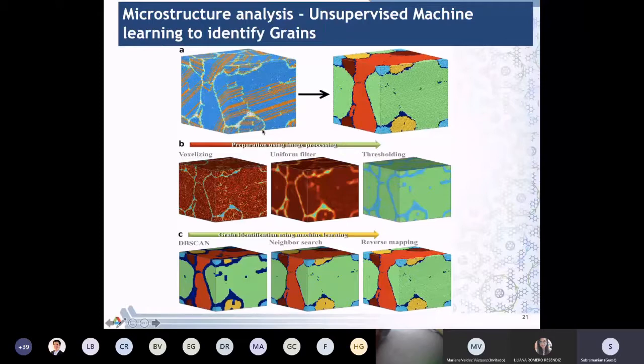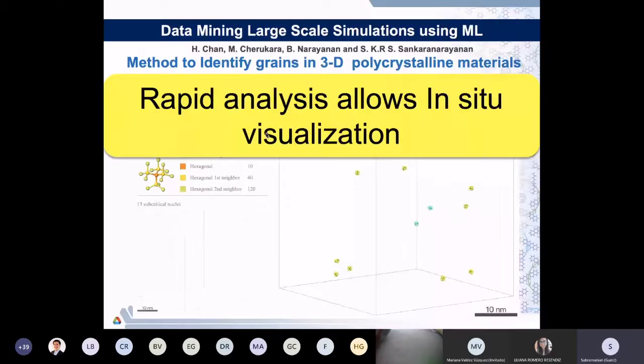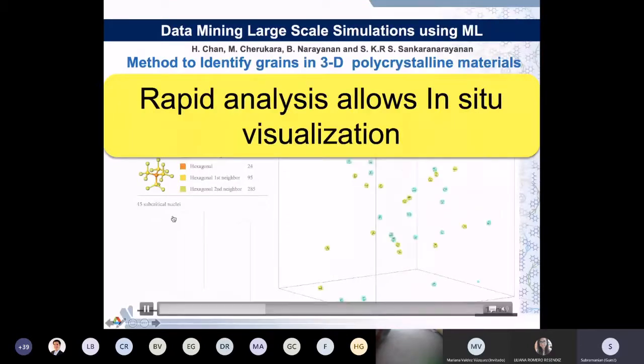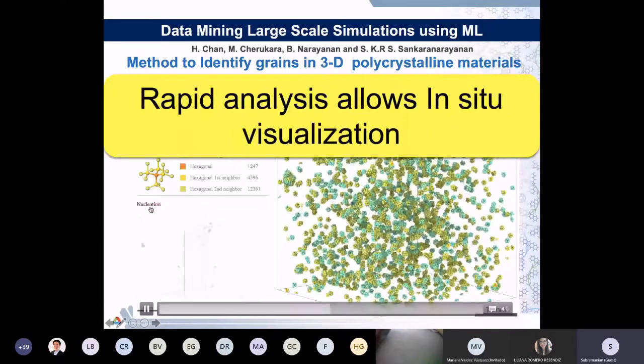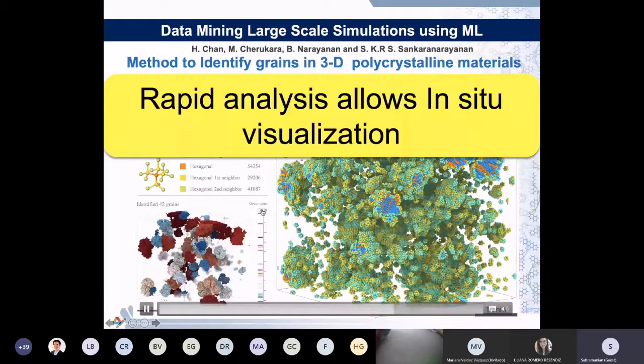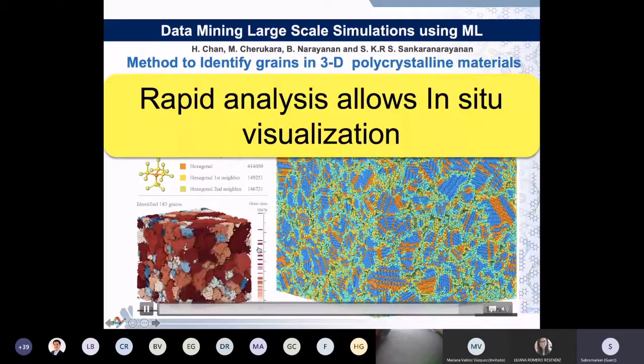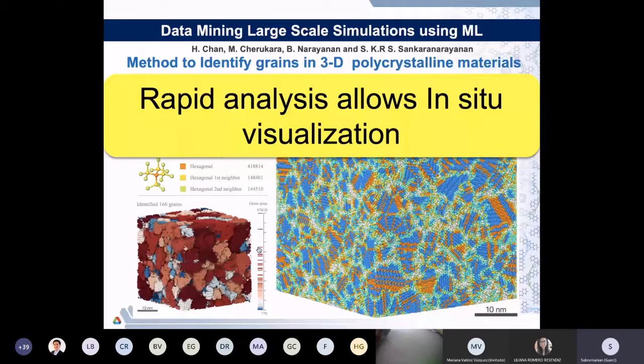The advantage of that is that as you are performing the simulation, you can actually do the analysis of how many grains are actually forming, whether they are subcritical, whether they are critical. And so you can actually map the grain size distribution in real time. So this is actually real-time in situ visualization as you are carrying out these large-scale multi-million molecule or billion molecule simulations. This actually takes only a fraction of a second to do the analysis of the frames. So this is very, very efficient and can actually rapidly analyze these different grains.